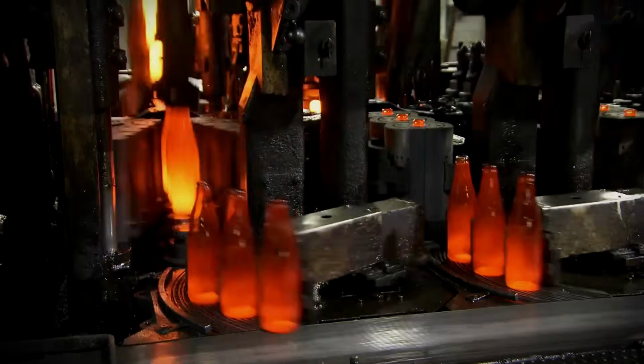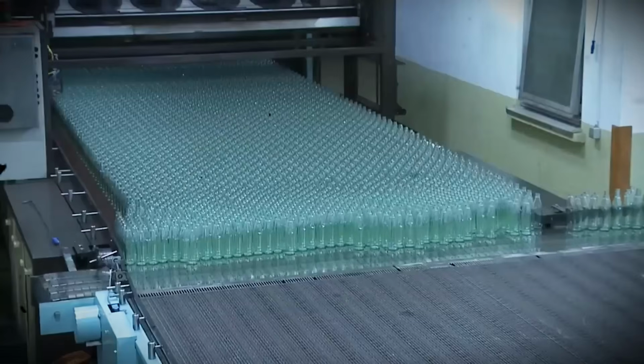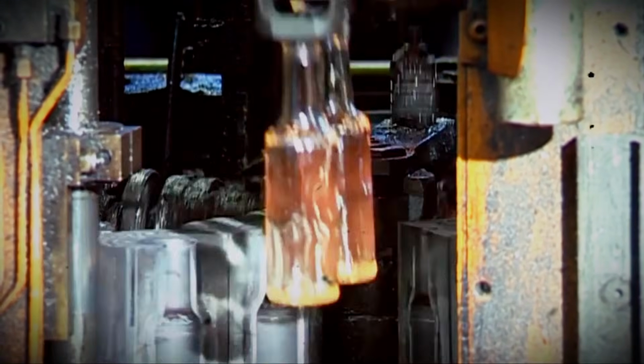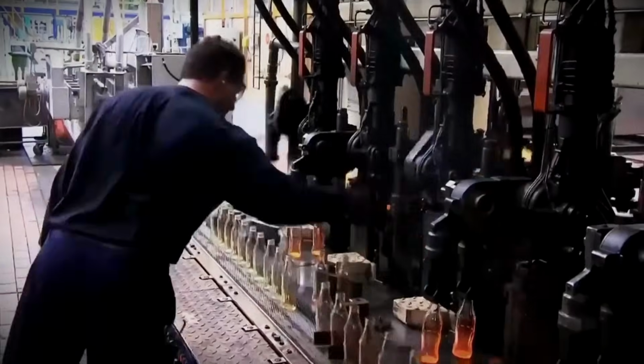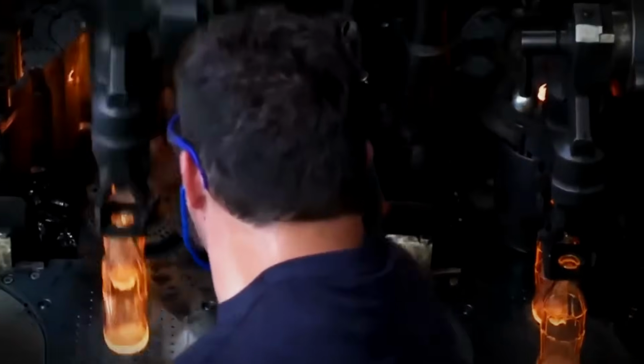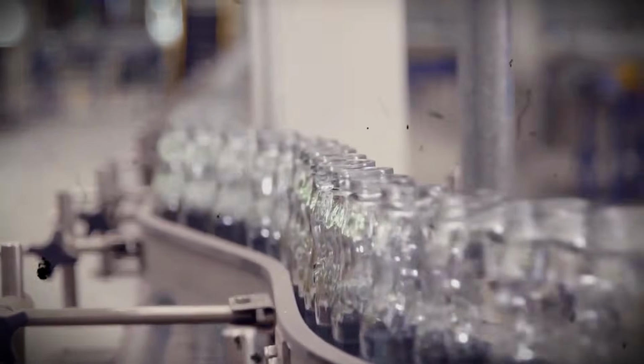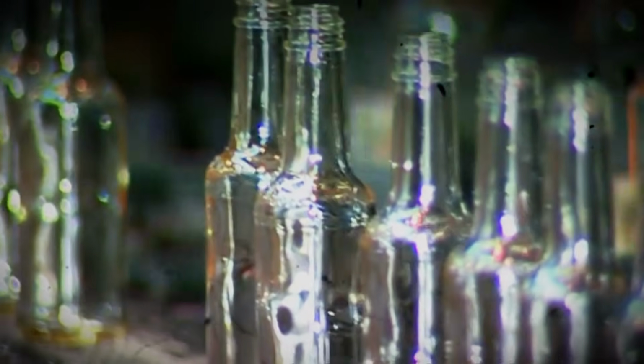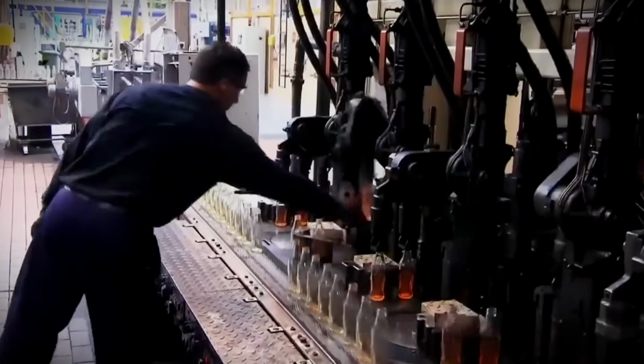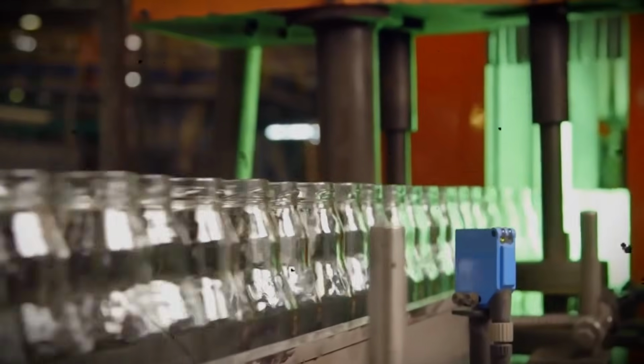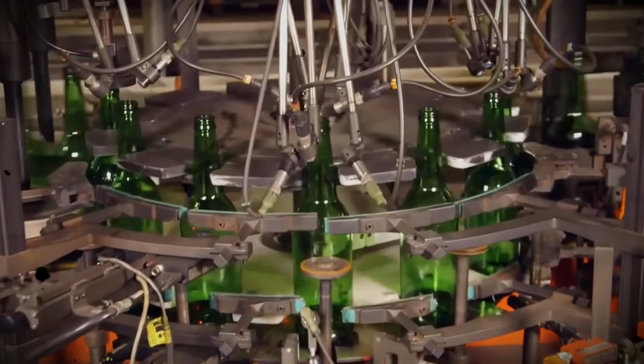Fresh bottles travel through an annealing layer for 30 to 45 minutes, cooling gradually. Then, every single bottle faces automated inspection. High-speed cameras check for cracks and defects. Infrared sensors detect stress patterns. Bottles must withstand at least 90 pounds per square inch internal pressure. Any failures get crushed and recycled back to the batch house.